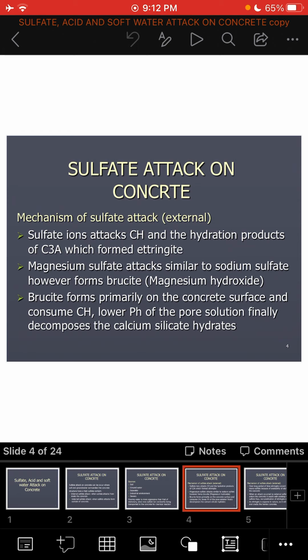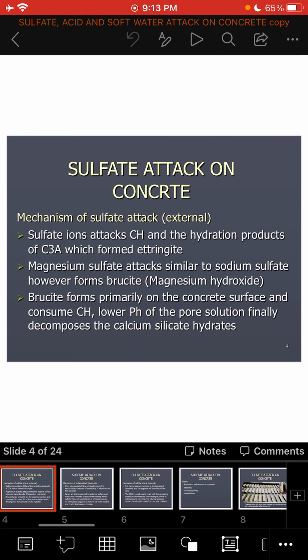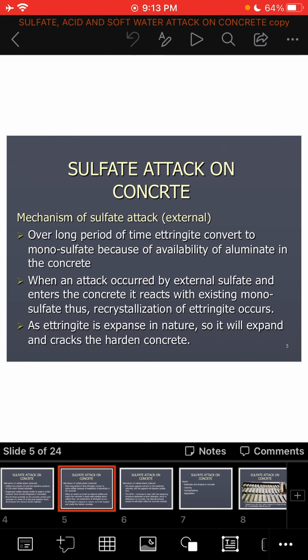Magnesium sulfate attacks similarly to sodium sulfate, however, it forms brucite. It primarily forms on the concrete surface and consumes calcium hydroxide. Lower pH of the pore solution finally decomposes the calcium silicate hydrate. Over a long period of time, ettringite converts to monosulfate because of the availability of aluminate in the concrete.